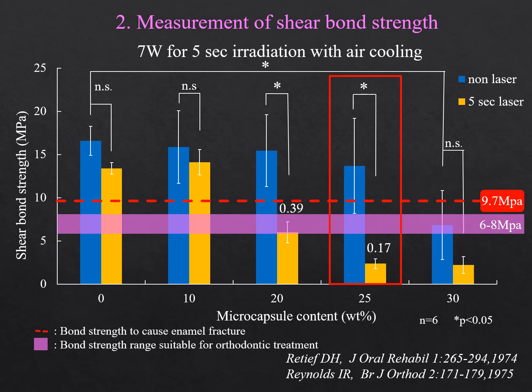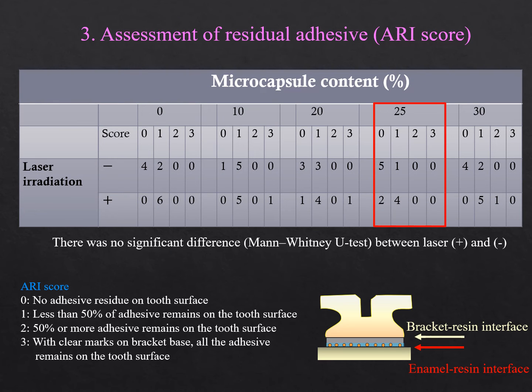In this study, a light-cured adhesive with a microcapsule content of 25 weight percent had suitable bond strength for orthodontic treatment, and irradiation with a CO2 laser for 5 seconds significantly reduced the bond strength. In the evaluation of ARI score, there was no significant difference between the laser irradiation and the non-irradiation groups in the groups containing 0 to 30 weight percent of microcapsules.